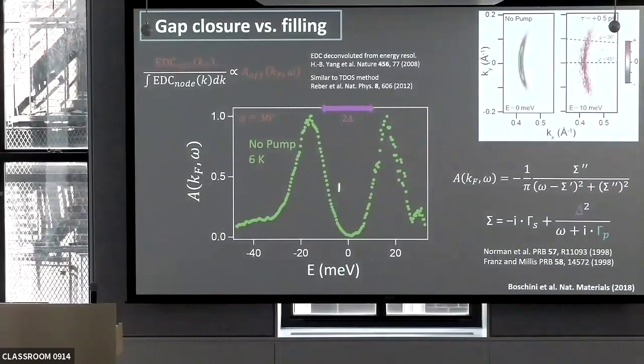This is actually not just divided off, it's a deconvolution that Fabio has done, where resolutions are also taken into account. So deconvolving the whole thing, you can get this kind of data. Just keep in mind, there is no pump. It's not like we are heating up the sample with a laser. So this is the low temperature data, and the gap is very well defined.